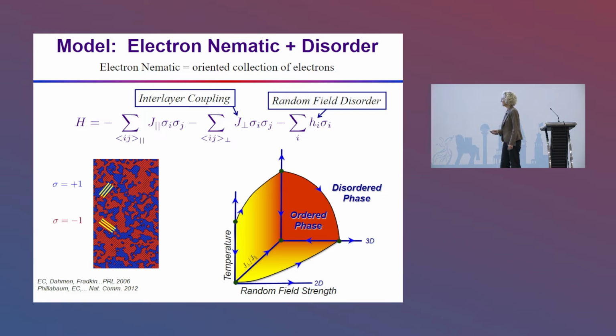So in this case, we have that the stripes are in one orientation or the other. An either-or variable you can model with an Ising variable. So I'll call stripes that are diagonally to the right, sigma equals +1. Stripes that are diagonally to the left, sigma equals -1. We make the reasonable ansatz that neighboring stripe patches want to be aligned. So that's a ferromagnetic interaction.